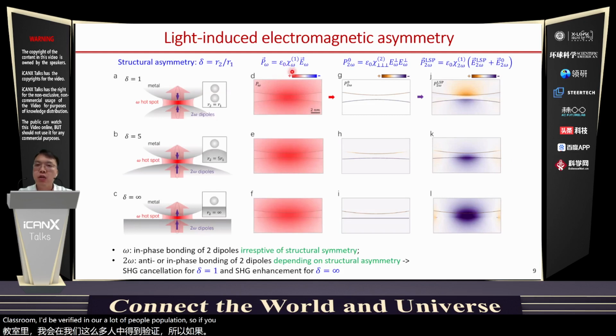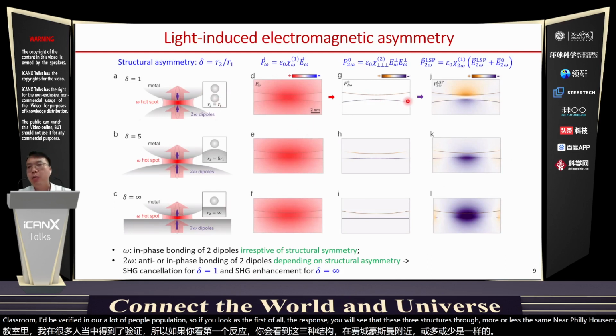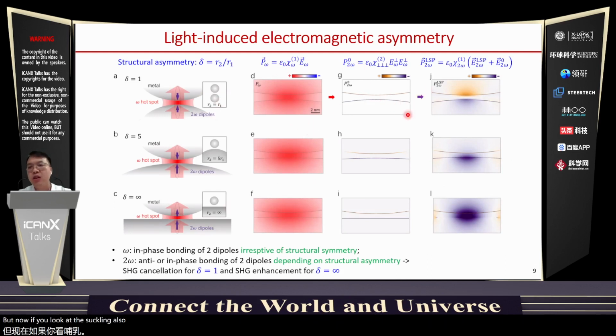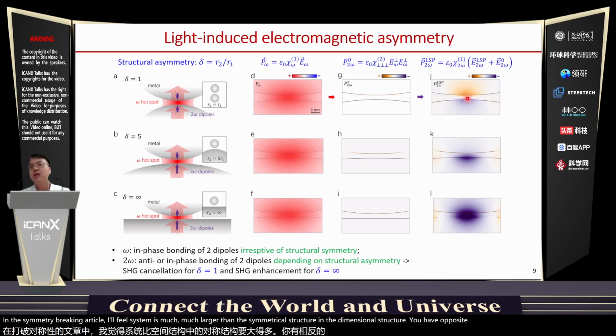So if you look at the first order response, you will see that these 3 structures show more or less the same near field enhancement. But now if you look at the second order response, you will find that the second harmonic generation, second order polarization field in the symmetry broken particle on film system is much larger than the symmetrical structure. Actually, in the symmetrical structure, you have opposite second order polarization fields.